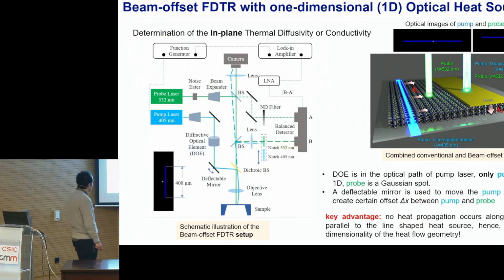Now, another way that we recently developed in my lab is to measure the thermal anisotropy in these materials by creating a unified thermal characterization system. So we don't have to take the sample and measure it in another setup. This is happening in one setup. So this is a unified setup, where we are using a line-shaped heater. Instead of having a Gaussian spot, we have a line-shaped heater. And then we have a Gaussian spot, which is next to the line-shaped heater, where we can measure the temperature.